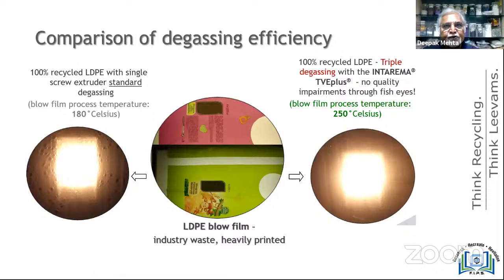And this picture shows for itself the comparison of degassing efficiency. The picture on the left is with the standard conventional extruder with degassing capabilities not up to the mark, and you can see the fish eyes or the bubbles in the film. And on the right is with the triple degassing, and you can see the nice surface without the gases, without the bubbles, without the fish eyes.